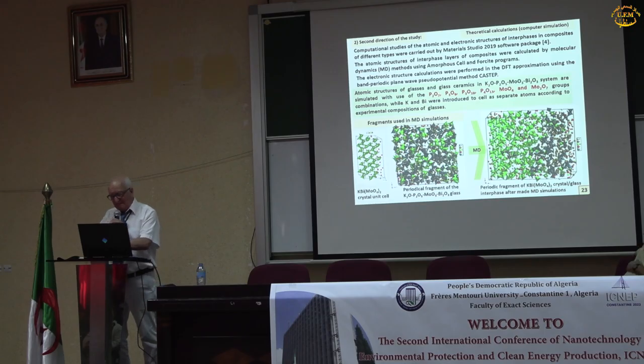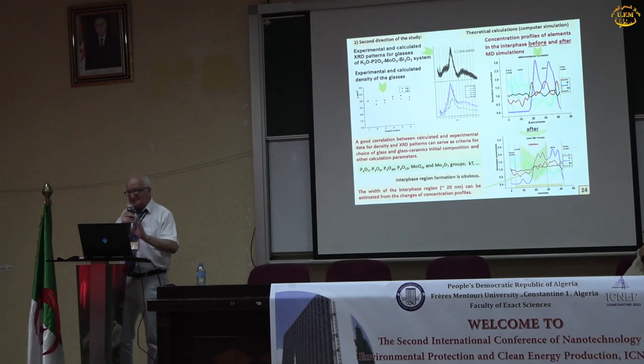So they form this interface layer. Then we compare this data about some experiment, especially with density of the composite materials, with XRD data, and we see a good correlation between calculated and experimental data for density and XRD patterns, and this correlation can serve as criteria for choice of glass and glass ceramics initial composition and other calculation parameters.